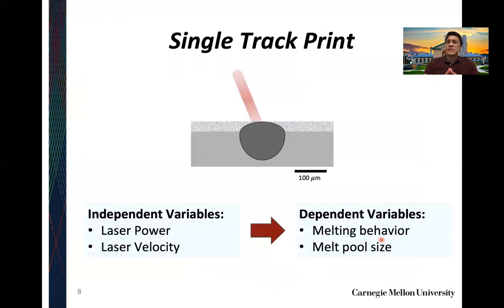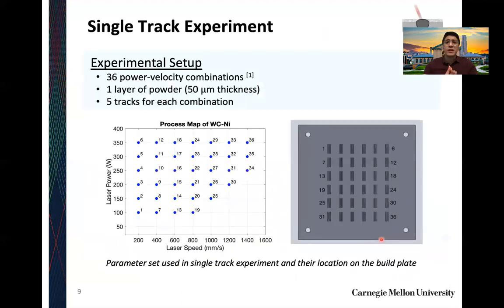Now, with regards to the single track print experiments, as I mentioned before, our independent variables were laser power and laser velocity, and we just wanted to evaluate the melting behavior as well as the melt pool size of our powder. Experimental setup, we used 36 different power velocity combinations. We only did one layer of powder, 50 micron in thickness, and we did a total of 5 tracks for each combination for a total of 5 times 36 different laser tracks.